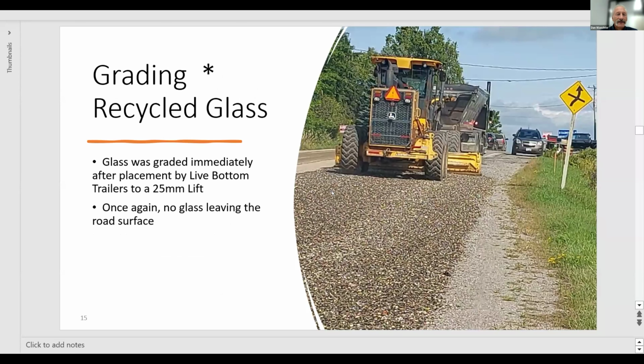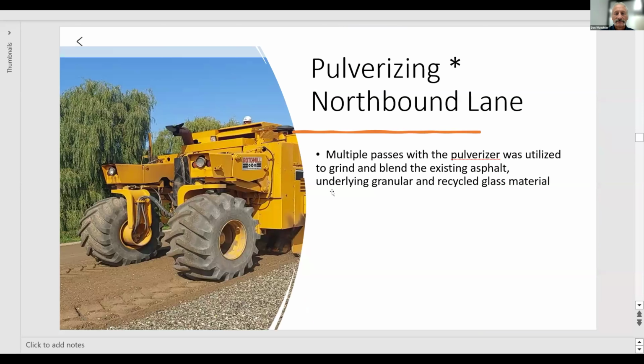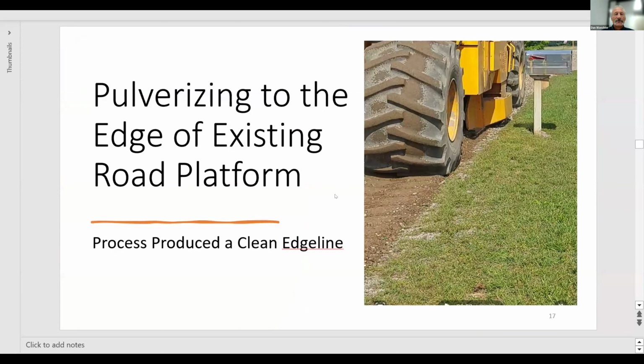Glass was graded immediately after placement to a 25-millimeter lift. Once again, you can see no glass leaving the road surface. Multiple passes with the pulverizer were used to grind and blend the existing asphalt, granular, and recycled glass. Pulverizing to the edge of the existing platform produced a clean edge line, also high priority for us.